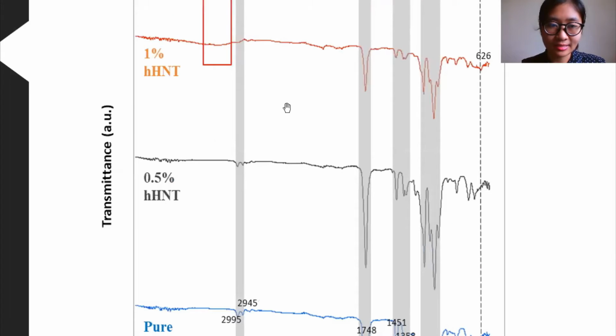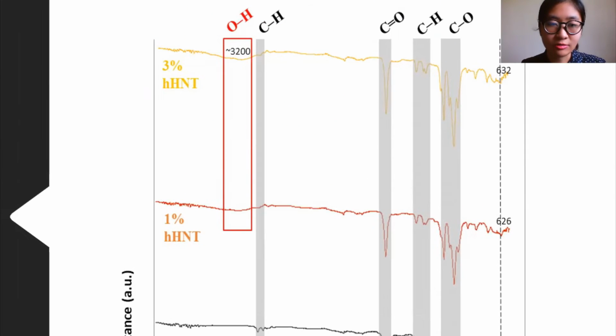At increasing clay content, a broad signal was observed at around 3200, which indicates the presence of oxygen-hydrogen bonding. This in turn has affected the signal of the carbonyl bond stretch for PLA. The intensity of the carbon-oxygen double bond was observed to decrease at 1% HHNT and 3% HHNT, which may indicate a weakening of the dipole moment due to formation of OH bonding. It is suggested that the incorporation of a higher concentration of HHNTs affected the strong peak signals at 2995 and 2945 wave numbers originally detected in the PLA spectrum.